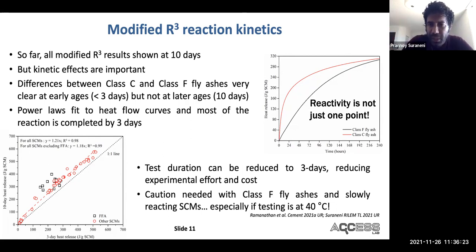So this reactivity is important to consider because you simply cannot say that class C and class F fly ash are the same, because they are not. And most importantly, the behavior we are seeing in the reactivity test is actually reflective of the behavior in concrete.